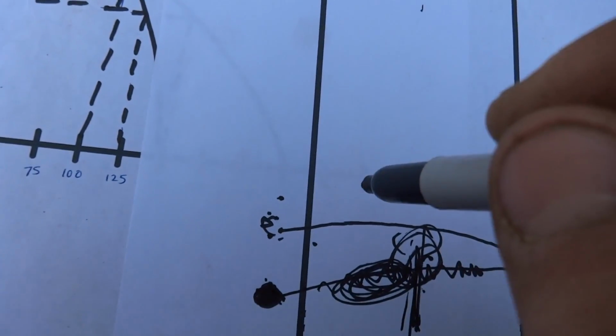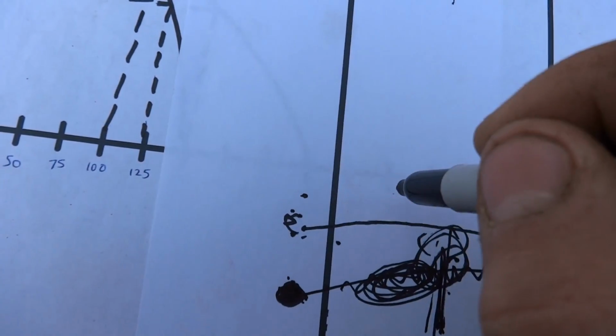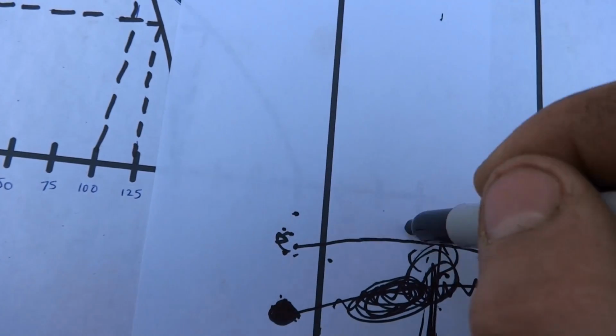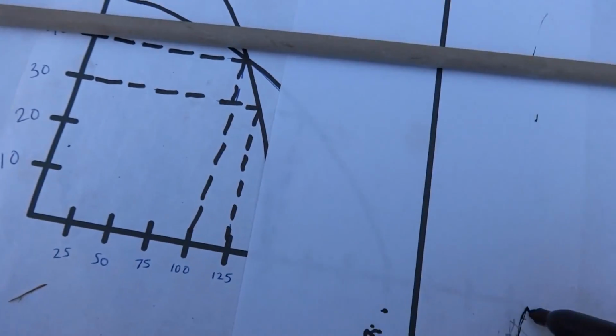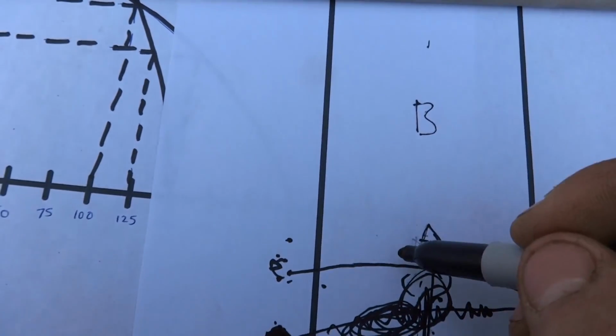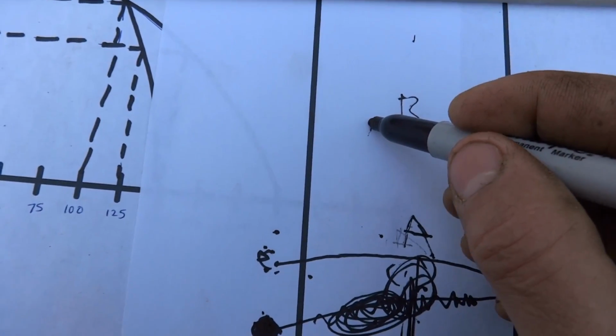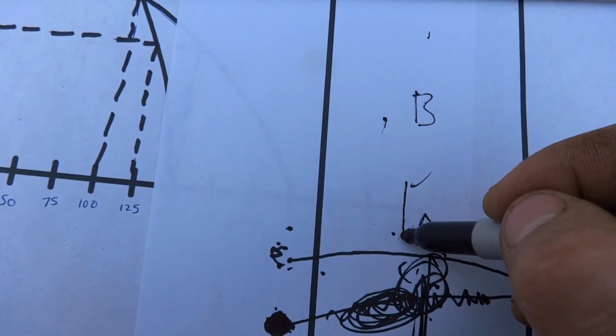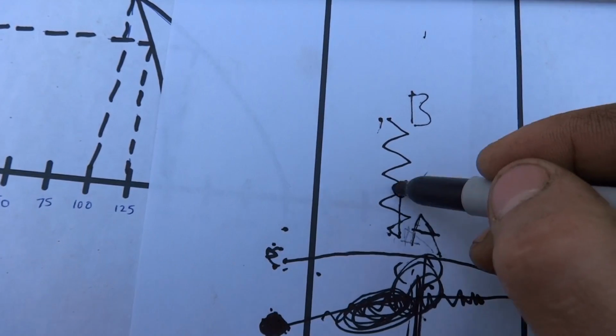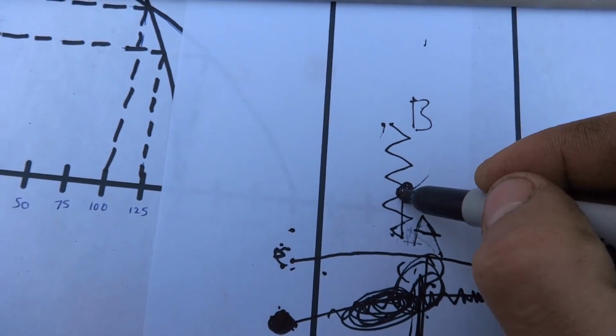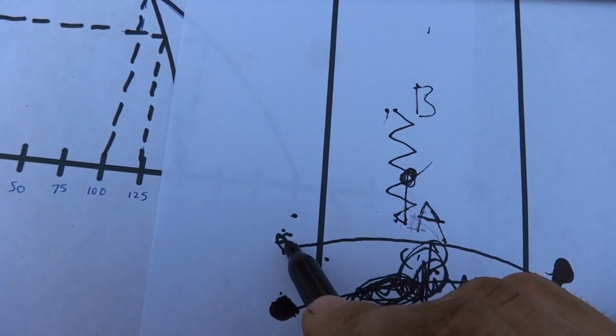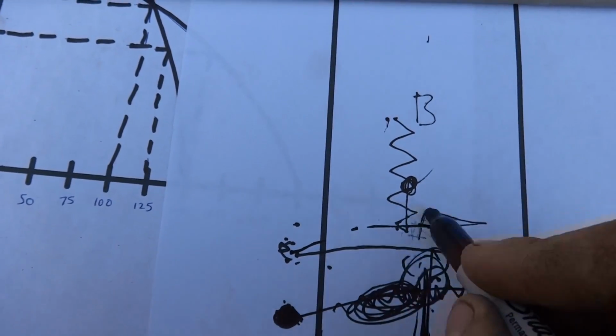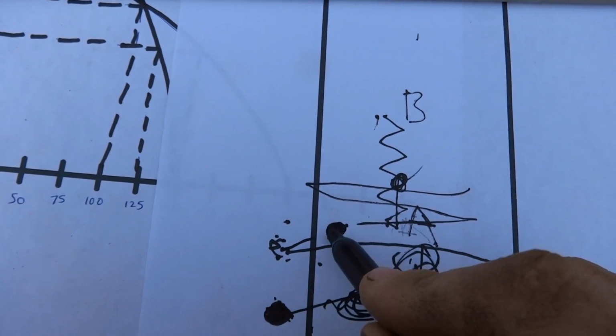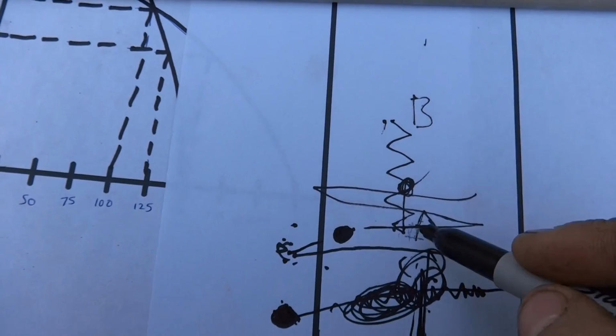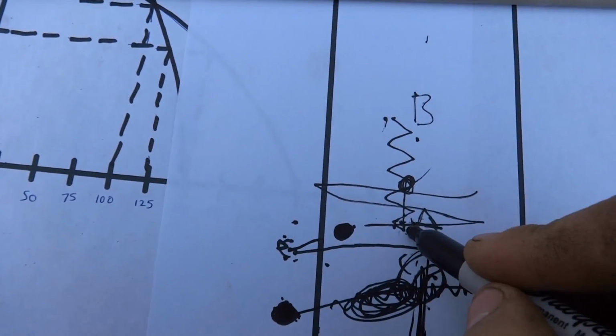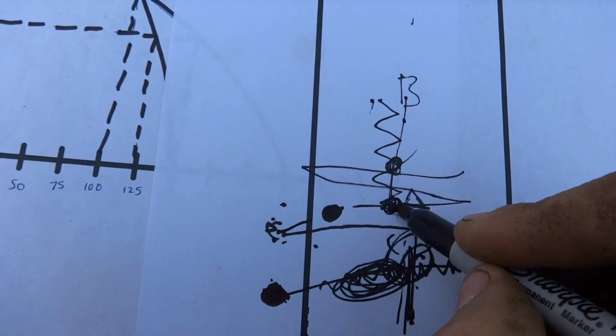That's the same as, if you want to strike an arc, just touching and then just start welding. If you're doing a weld from A to B with a 7018 electrode, you have to scratch start right here and then come down to A and then start welding, because you'll leave surface porosity right here. However, when you snuff out the electrode down here, the electrode suddenly reignites and you keep welding, you just put porosity right there. That's the very same as saying, I want to weld from A to B, I'm just going to touch the electrode right here, and I'm just going to start welding. You're going to get surface porosity right there.